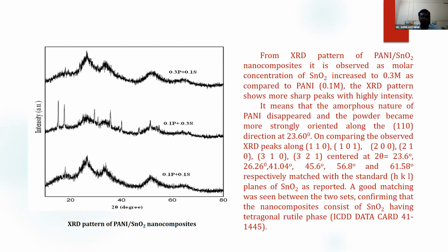So again, I have taken the XRD pattern of the PANI and SnO2 nanocomposite. The middle graph shows some peaks. The other two samples, where the molar concentration of polyaniline is higher, show the amorphous nature of polyaniline, a polymer, not a crystalline nature. But when I increase to 0.3 molar concentration of tin chloride, tin oxide, then some peaks are observed, which indicate the formation of PANI SnO2 nanocomposites.